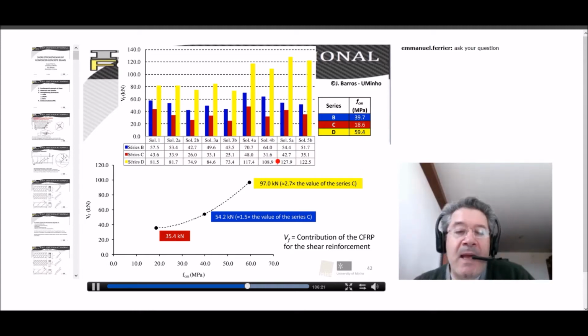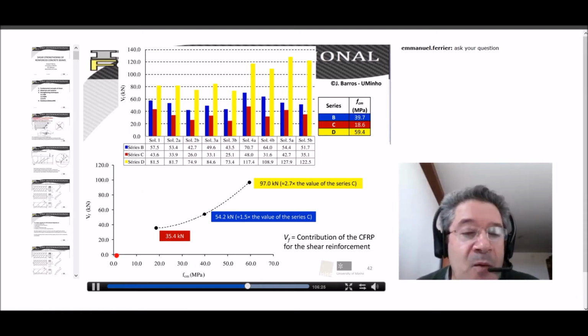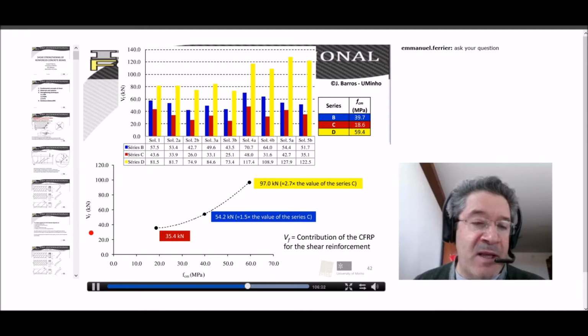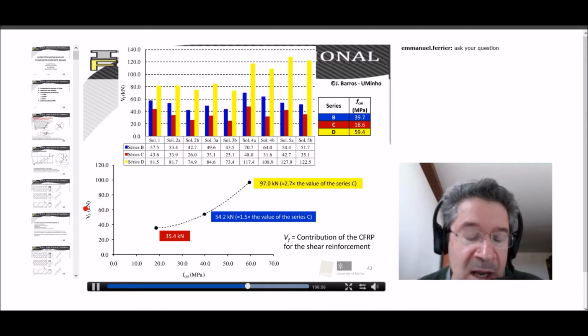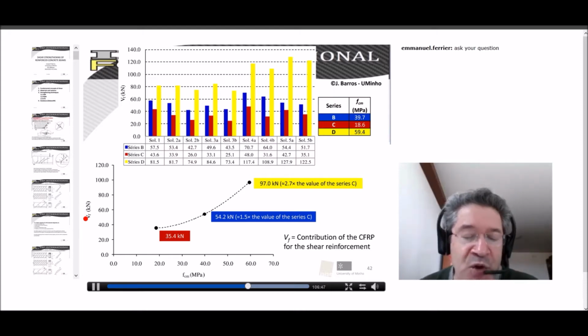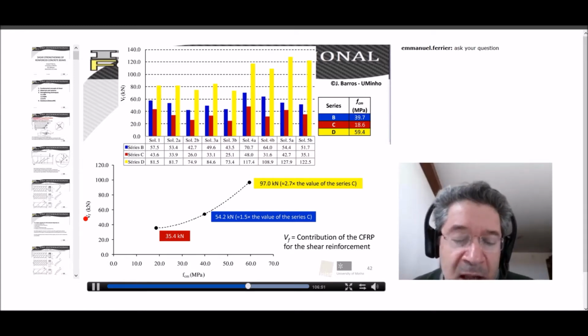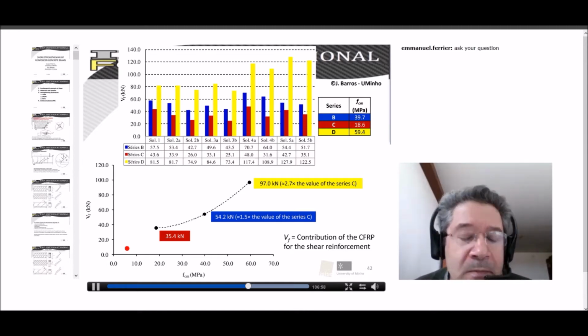And in this graph, we have a relationship between the contribution of the FRP system that was composed by laminates. In this case, we use FRP laminates of cross-section 1.4 millimeter by 10 millimeter. So we use rectangular cross-section laminates of 1.4 millimeter by 10 millimeters. And it is quite clear that when we increase the compressive strength of the concrete, the contribution or the effectiveness of the CFRP laminates increase significantly.